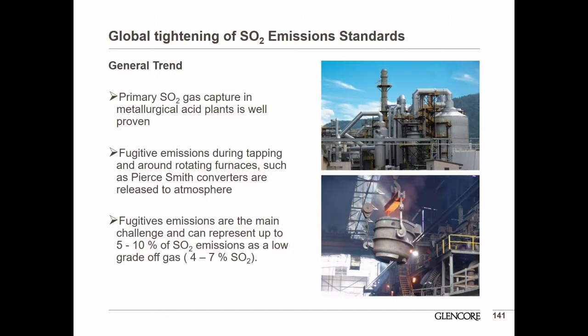The remaining problem though is fugitive emissions, and these are emissions where you'll get puffing around furnace ports, and these can account for about 5 to 10% of SO2 emissions around smelters. In a modern smelter, less than that, but in a lot of the traditional smelting network globally, you can get that much SO2 loss, and it is as a low-level gas. It's very difficult to capture, very expensive to treat. You can see in the photograph on the bottom right-hand side of the screen, this is a pot movement down a converter aisle, and this is a very common source of fugitive emissions in smelters at the moment.